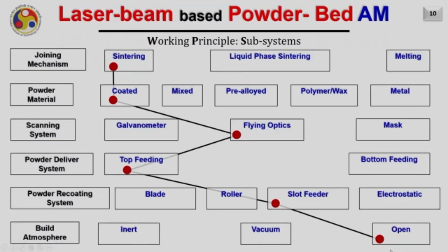Another variant of the system is when sintering is used for joining the powder particles. The powder material is again the coated particles. Flying optics is used to scan the laser beam onto the powder bed. Material is fed from the top side and a slotted feeder is used to spread the layer of powder. And then the whole thing happens in an open environment, and hence the layers are joined in the open environment without using any vacuum or inert environment.